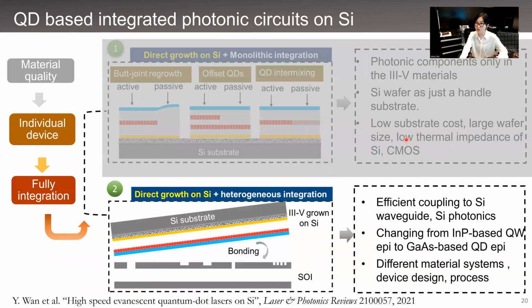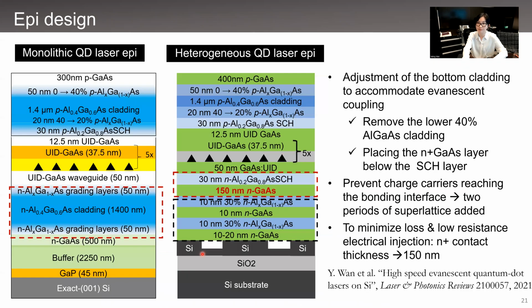And for the second direction, to integrate quantum dot-based photonic integrated circuits on silicon, we not only use silicon as a substrate. Actually, we aim to achieve low-loss active-passive coupling of III-V with silicon waveguides, and this is something really silicon photonics. So in this case, compared to the standard heterogeneous process, it requires changing from indium phosphide-based quantum well epi to gallium arsenide-based quantum dot epi, and thus we need different material systems and thus very different device designs and process optimization.